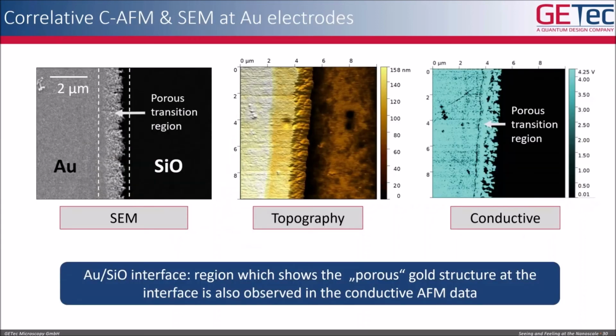Now I want to show you some examples. We use these tips first for a very simple example: we measured a gold electrode on a silicon substrate. On the left part, you see the SEM image, where the bright part is the gold electrode. You have a porous transition region due to some etching during fabrication of the electrode, and this is all on a silicon substrate. Of course, you can measure the topography, which you see here with the AFM.